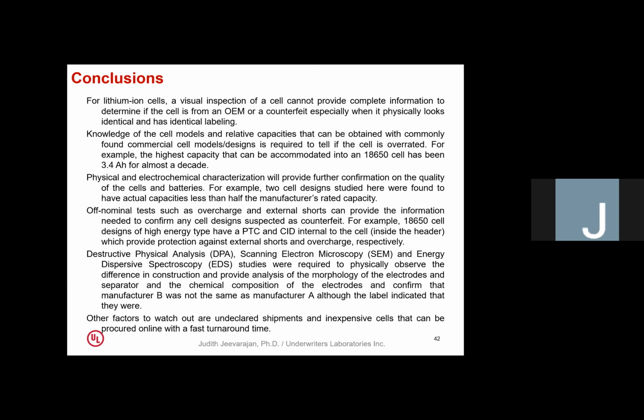The physical and electrochemical characterization will provide further confirmation on the quality. And we did find that there's a difference in the capacities when you measure them. Off-nominal tests also provide more information on whether these are real or counterfeit cells. And it's very easy, even just looking at the voltage curves, you can tell the difference between a cell that has a PTC and one that does not. Destructive analysis and SEM-EDS are also required to physically know the difference in construction, and also provide analysis on the morphology of the different components as well as the chemical composition, if you want to know whether these are really authentic or not.